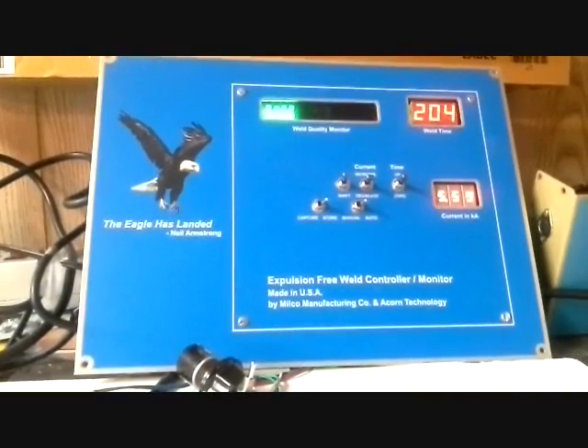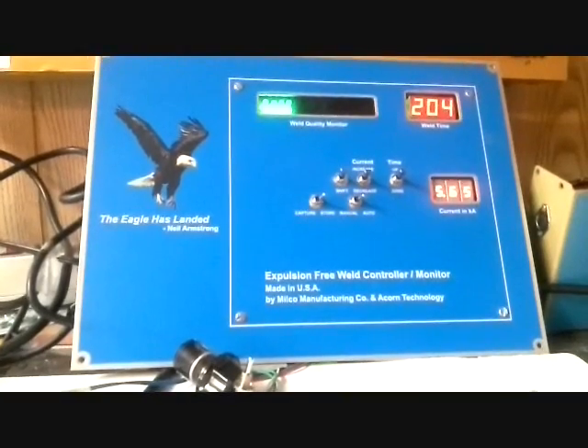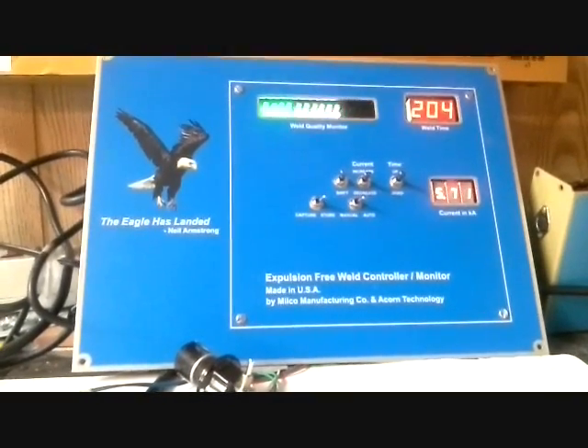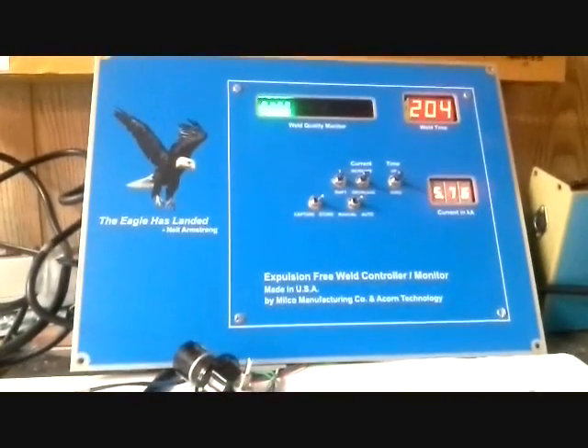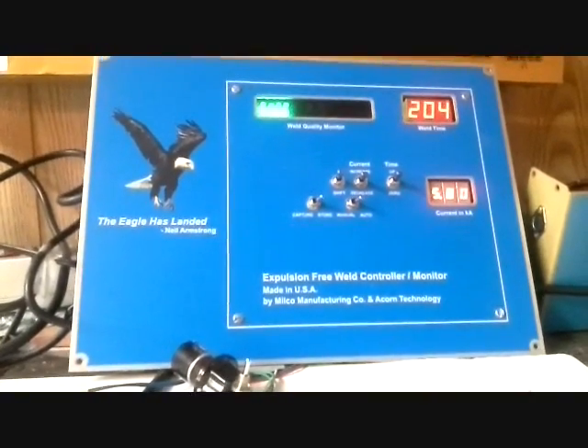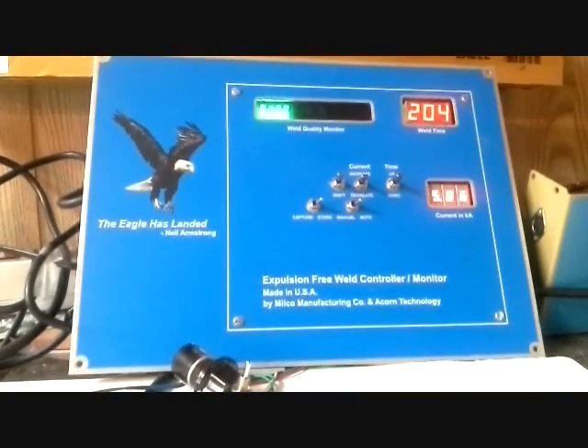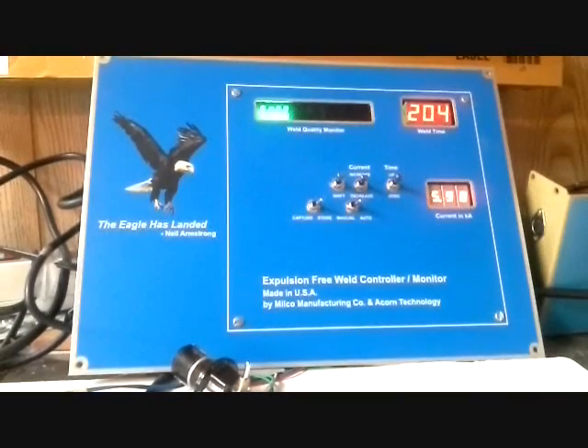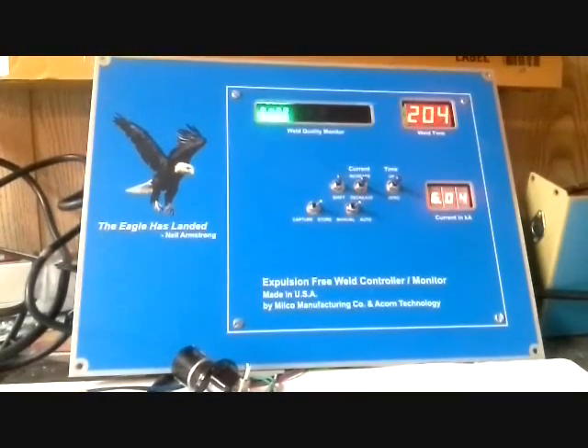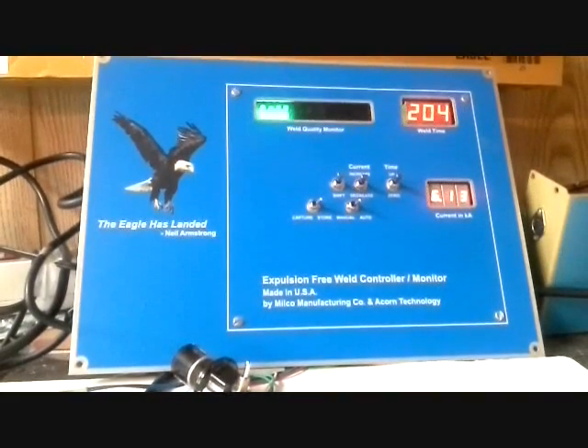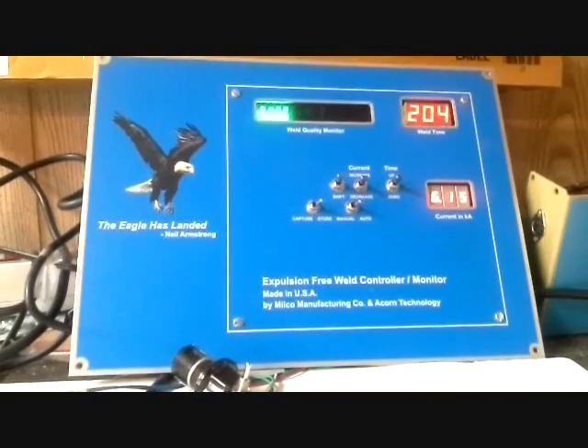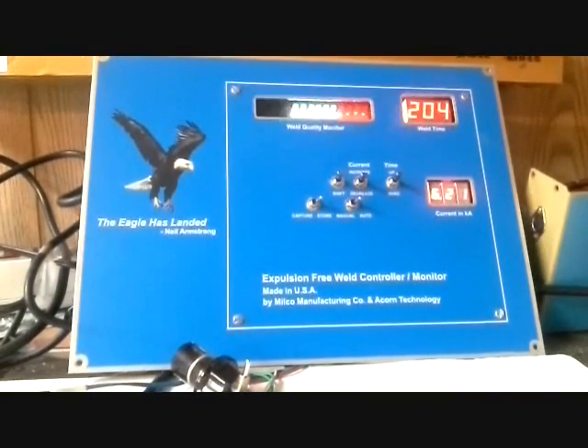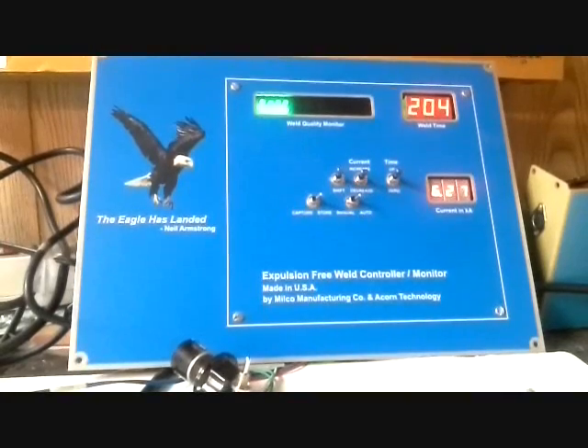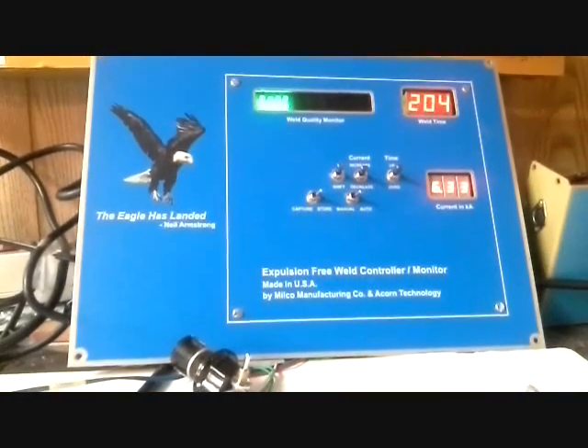On the production line, when your weld caps start growing larger and larger, if you keep the same weld schedule, the temperature at the center of the nugget will become lower and lower. This weld controller senses the temperature, so it will increase the current until the estimated diameter of the nugget goes back to the right amount.